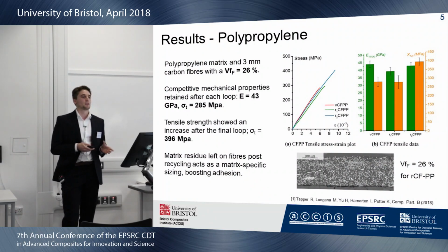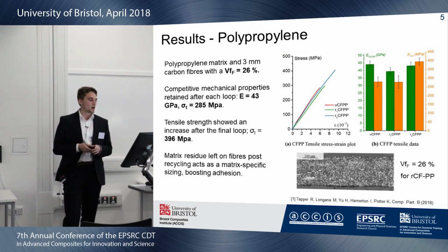I did this with polypropylene and 3 mm carbon fibres, and got an average volume fraction after each iteration of 26%. And from that, we got competitive properties, even with virgin discontinuous carbon fibre polypropylene, and to have a stiffness of 43 gigapascals and a strength of 285. And you can see from the tensile stress strain plot and bar chart that the stiffness is unwavering through iteration. But what we actually see is in the final recycling loop that the strength increases.